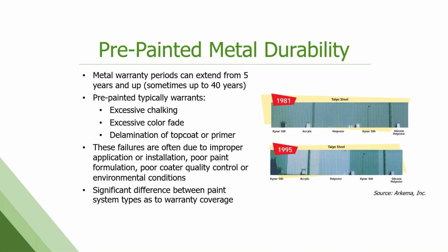So the durability of this product can be anywhere from 5 years and up. Like I said, we are starting to see warranties in the 40 to 50 year range. Typically, pre-painted warrants excessive chalking, excessive color fade, and delamination of the top coat or primer to the substrate, which is also what we call film integrity. These failures can occur for a couple different reasons. It can be improper application of the paint by the coater, it can be installation issues, it can be a poor paint formulation, it can be environmental conditions at the site. But we do see significant difference between paint system types as far as performance and warranty coverage.